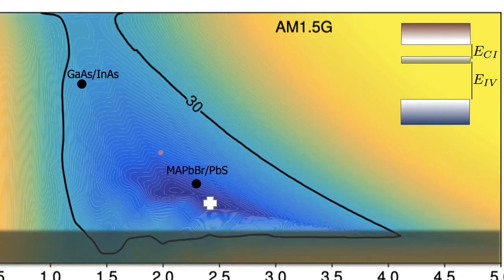So some of the intermediate band devices that have been made so far are quantum dot systems. So the most studied one is gallium arsenide with indium arsenide quantum dots. So that's a small region of indium arsenide inside of gallium arsenide. And I've just shown not the efficiency of these, but where they appear on the band gap space, if you just take them as an intermediate band and as a semiconductor. And then there's also this hybrid perovskite, methyl ammonium lead bromide with lead sulfide quantum dots, which you can see from a band gap perspective is extremely close to our optimal band gaps. There are highly mismatched alloys.